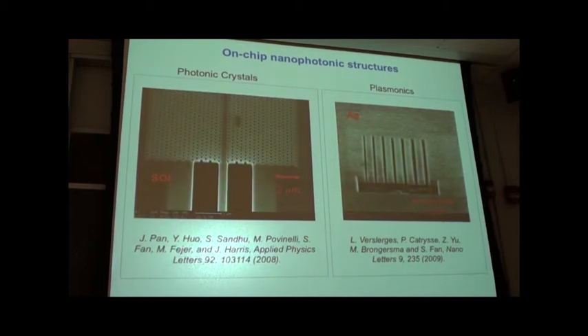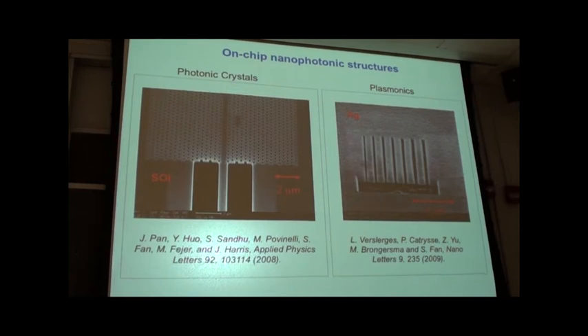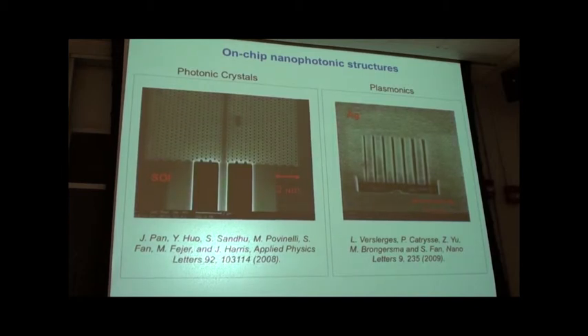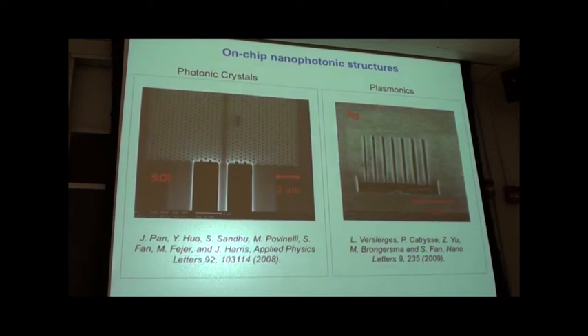On the right is a plasmonic structure made by my student: a roughly hundred-nanometer-thick silver film with an aperiodic array of slits introduced by FIB etching, where the narrowest slits are on the order of 30 nanometers. We actually made it into a lens for focusing light in image sensors. We are generally quite interested in these classes of structure for control of electromagnetic waves, including applications in information technology, energy applications such as solar cells, and control of thermal radiation.